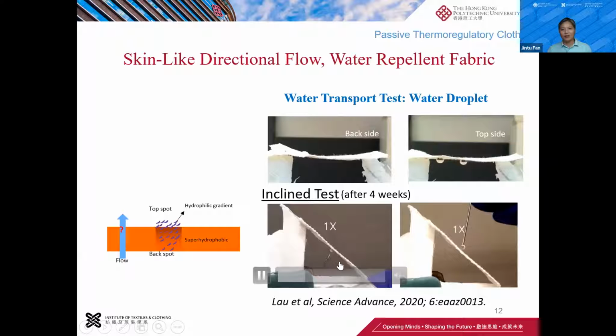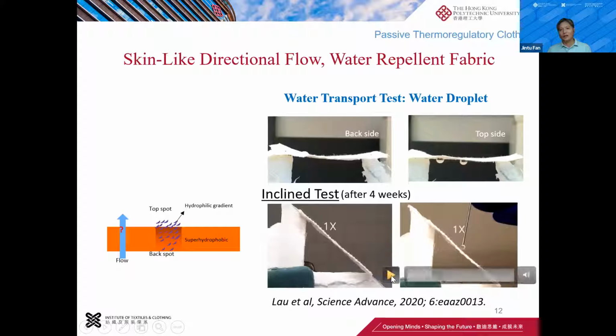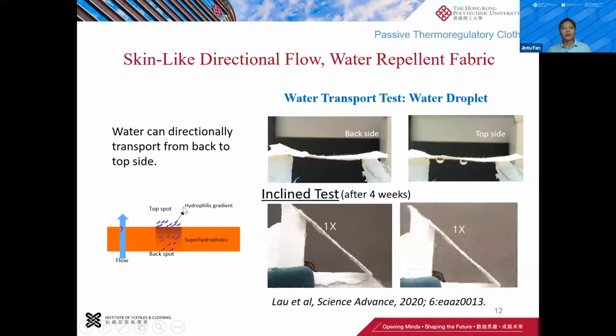So in this demonstration, you see a typical cotton fabric after treatment. Simulating the sweat from underneath, the liquid will go through the material to the hot surface and drop. And then if we supply external liquid, this fabric is water repellent. Right? So this is another way of, you can say, moisture management. The directional liquid flow is basically achieved by wettability gradients. In a lot of sportswear fabrics, we simulate things like sweat glands.